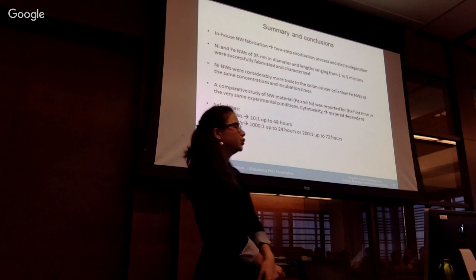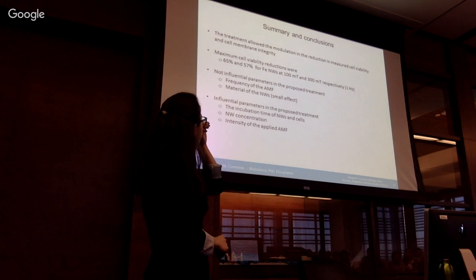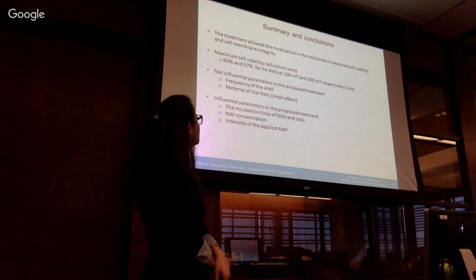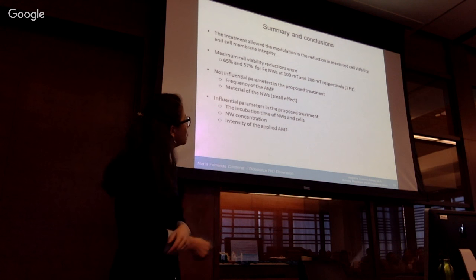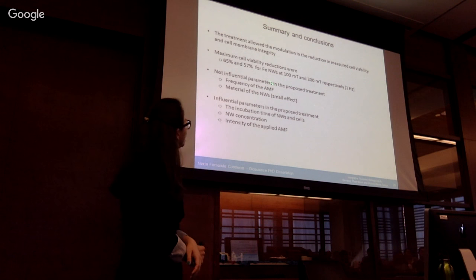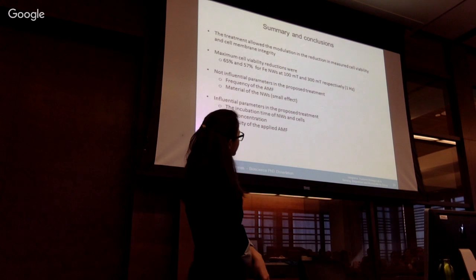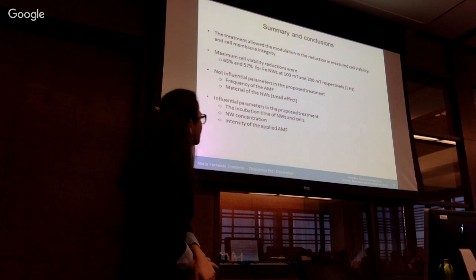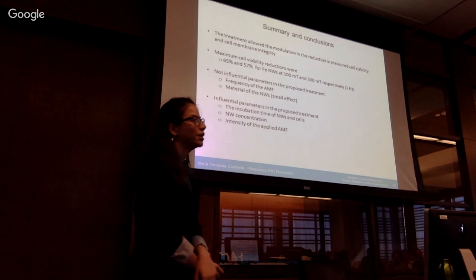And regarding the treatment, we found that the cell viability reduction could be modulated in terms of cell viability and membrane integrity by just changing the parameters we use. We see a broad range of around 20% reduction if we play around with the parameters. The maximal cell viability reductions found were 65 and 57% for iron nanowires at 100 milliteslas and 300 milliteslas of field, respectively. And the parameters that were not influential in our proposed treatment were the frequency of the field and the material of the nanowires, which only had a small effect.